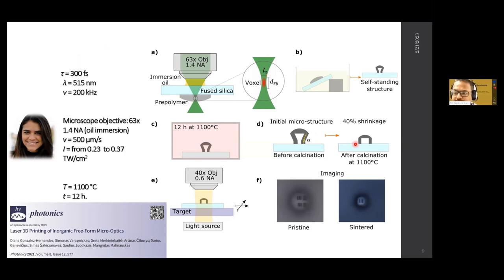At this stage, it's not absolutely clear how it will behave on fixed substrates. To some extent, it will shrink. It may start cracking or deforming. But if you allow it to freely shrink, it's just a reduction of mass and scale, but it's pretty proportional and repeatable. In this case, it was around 40%, both the angle and the shrinkage. If we would have more organic, it would shrink more. If more inorganic, it would shrink less. Yes. Okay. Thank you very much.